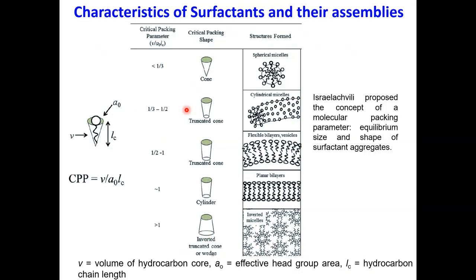Okay. Now, surfactant is one class of soft material, and I told you that surfactants can form assemblies as well, right? Surfactants are amphiphilic molecules where there is a head group and there is a tail, and they can pack differently depending on something known as the critical packing parameter. This critical packing parameter can lead to different geometries of surfactant assemblies. You can have spherical micelles, cylindrical micelles, lamellar phases, or inverted micelles. I just wanted to give you an idea that surfactants can form different assemblies, and these assemblies can be characterized by small angle X-ray scattering.